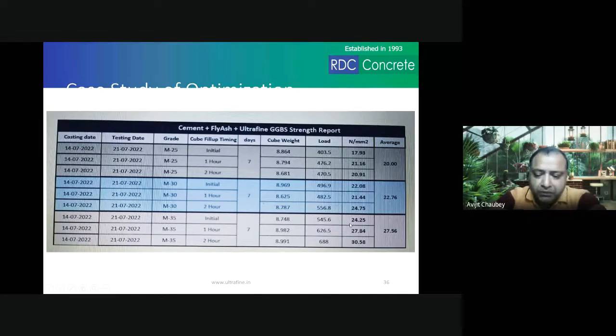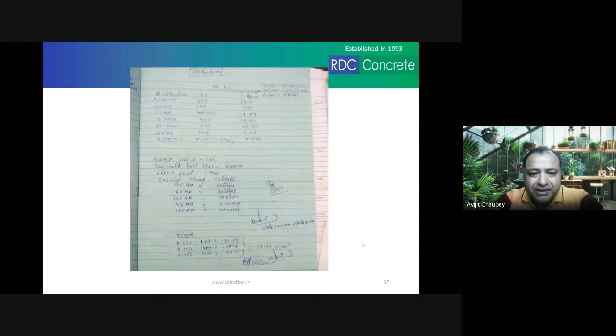So this is something beyond the ultrafine scope. This is the effect of mixing. The more amount of mixing gives you higher strength. Many people say that you'll get higher initial strength. No, initial strength you'll get lesser, but if you mix it for a longer time, you tend to get higher strength. This is because of the energy that you put in the mix to disperse the cement particles, so that all the cement particles hydrate, you definitely get higher strength for higher amount of mixing. Of course, this is the average that they got. They've calculated the average. But you see, they have significantly been able to see that the strength is higher for higher amount of mixing time.